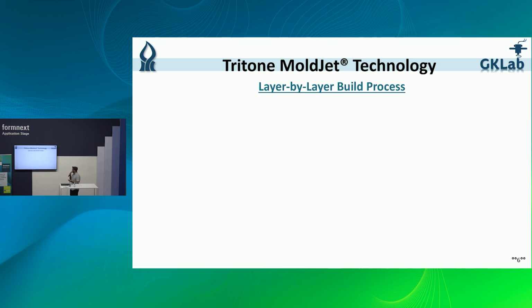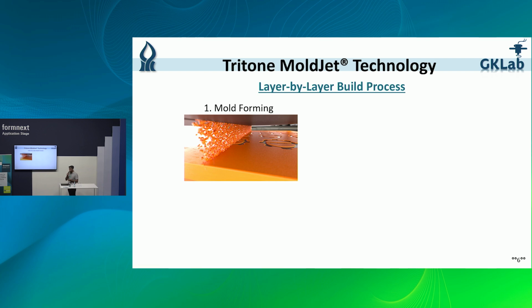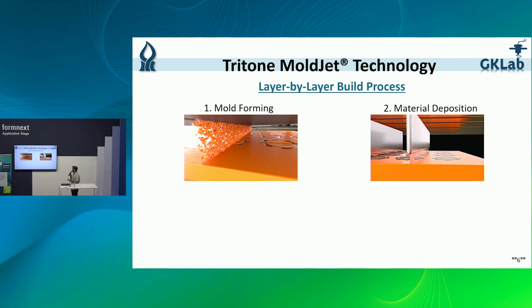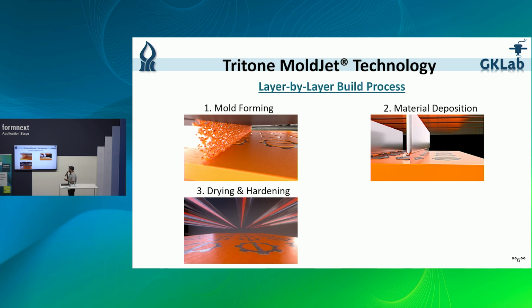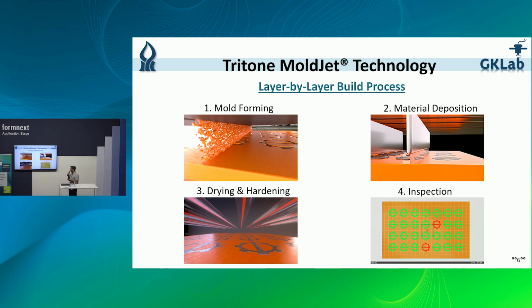Briefly, the layer-by-layer build process includes mold forming, in which a high-resolution print head jets an ultra-thin layer, creating a layer mold. Material deposition, in which a metal paste is applied into the molded cavities. Drying and hardening, in which the build rest goes into a thermal phase, hardening the new layer. And real-time visual inspection, in which a high-resolution camera analyzes the new layer, making sure it conforms to the final model. If it does not, the defective layer is removed, and the printer repeats the previous layer without affecting the process. This process repeats layer after layer at an industrial speed.